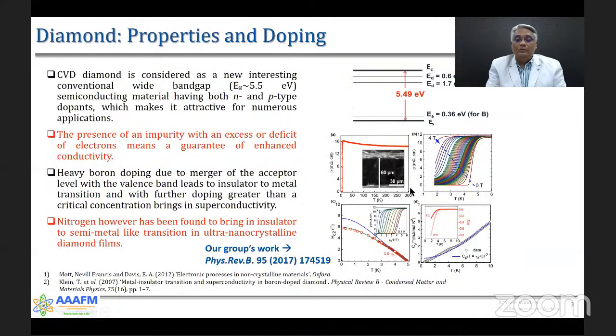So in our group, we have established a diamond growth process. We can make microcrystalline, nanocrystalline, and ultra nanocrystalline diamond coatings, thin layers, even thick layers, and for some measurements like specific heat. At high doping concentrations of boron, you find superconductivity in diamond, with superconducting transition temperature anywhere from 2 to 6 Kelvin. And the superconducting transition is very robust, and it doesn't vanish even at 4 Tesla of external magnetic field. The challenge, of course, is making it an N-type material,